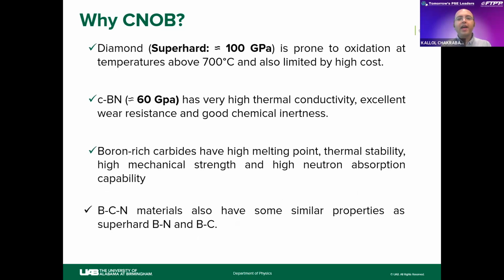As we know, diamond is a superhard material with a hardness around 100 GPa, but it has some limitations because it is prone to oxidation at around 700 degrees centigrade and is also limited by high cost. We cannot use diamond in applications where temperature reaches around 1500 degrees centigrade.